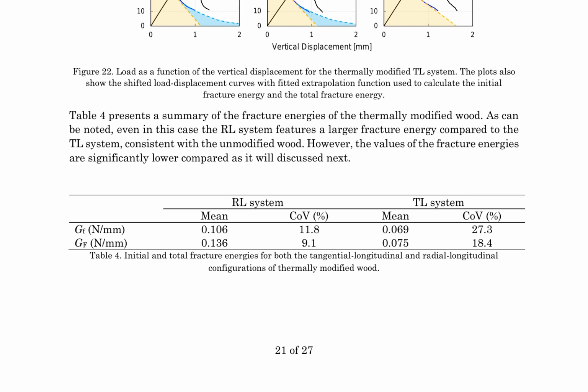These results suggest that thermal modification affects wood's fracture behavior, with implications for material characterization and potential applications. Notably, the fracture energy values are lower in thermally modified wood, indicating a potential decrease in material toughness. The data presented in Table 4 highlights the significance of considering both RL and TL systems when evaluating the fracture behavior of thermally modified wood.